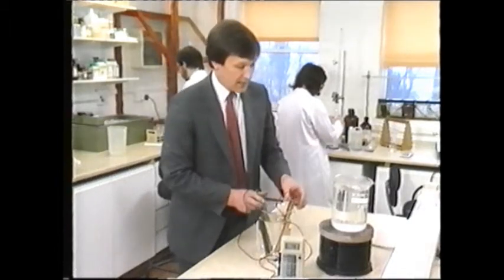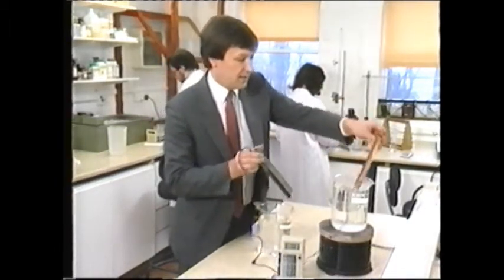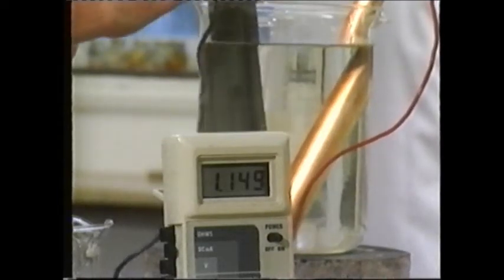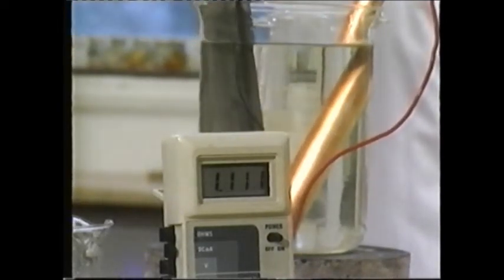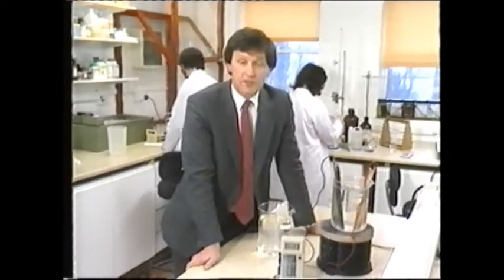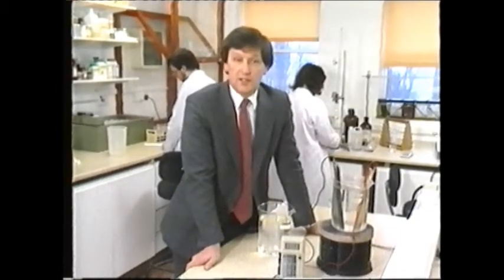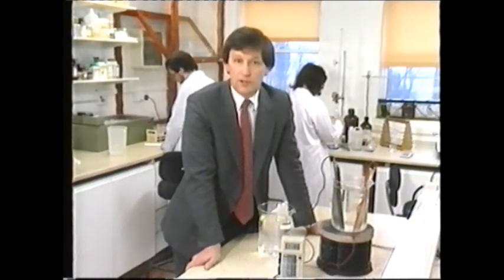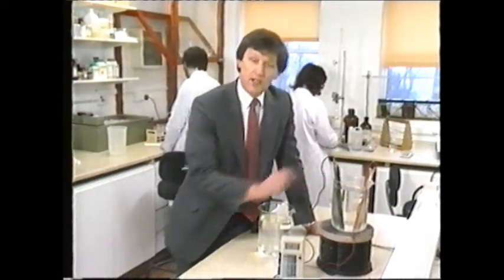Unfortunately for heating systems, the higher the temperature of the water, the higher the rate of corrosion. Apart from the simple presence of dissimilar metals, electrolytic corrosion can be promoted, for example, by the different constituents of an alloy and impurities in the individual metals themselves, particularly radiator steel, for which no British standard exists. Magnified 200 times, this is the result. Short-circuited electrolytic cells on the surface of the radiator steel. The effect is pitting and eventually pinhole perforations.